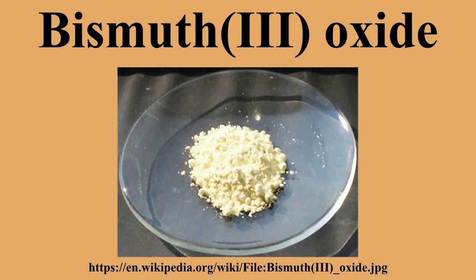Even though it is formed by heat, it reverts to alpha-bismuth trioxide when the temperature drops back below 727 degrees Celsius. Delta-bismuth trioxide can be formed directly through electrodeposition and remain relatively stable at room temperature.